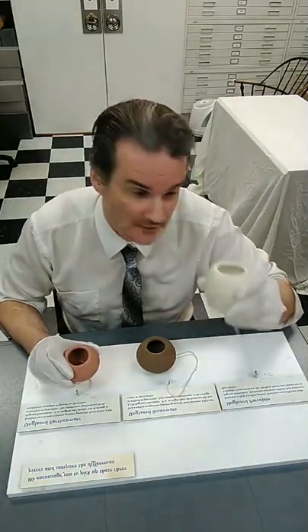A lot of the main difference — of course there's clay difference — but really the deciding factor is the temperature at which it's fired. There are clays specific to different types. The earthenware is fired up to about 2,100 degrees. Fired below that, you're generally going to get an earthenware, and it's going to feel a little bit rougher when you pick it up.